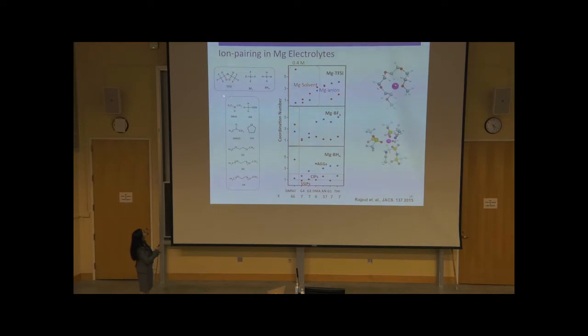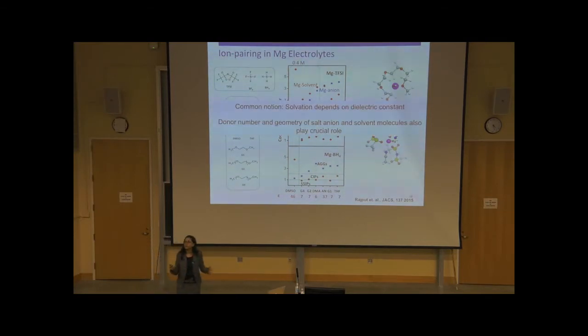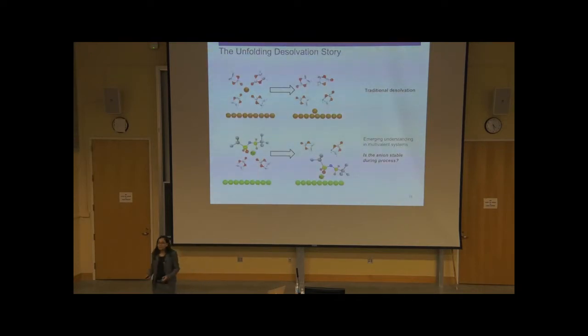We also found that the geometry of anions plays an important role. A big anion like TFSI, which has larger geometry and more dispersed charge, has a lower degree of ion pair formation compared to smaller anions such as BF4 and BH4. So the take-home message from these results is that solvation structure is a more complicated phenomenon and cannot be simply understood by looking at the dielectric constant of a solvent. The other factors that you need to keep in mind are the donor number and the geometry of the salt anion and the solvent molecule.